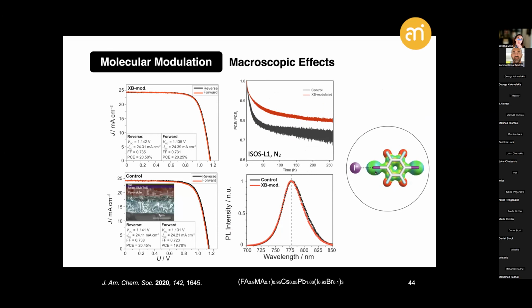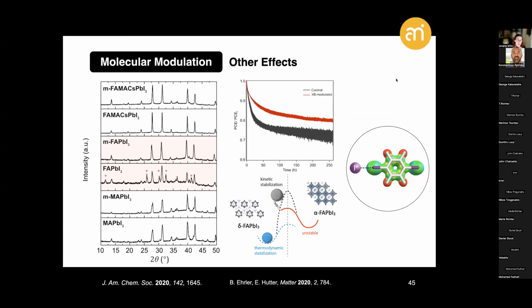However, looking more closely into these ion migration properties and seeing a minor change in the activation energy for these halide migrations in the presence of the modulator stimulated us to further look into these H samples, for example, looking for more insights into the modes of stabilizing the resulting materials, seeing in particular something interesting for the formamidinium lead halide-based materials, which are very appealing from the perspective of their optoelectronic characteristics, but which have this major challenge of being thermodynamically inaccessible at ambient conditions, under which they form this non-perovskite delta phase that is optically inactive, the so-called yellow phase,